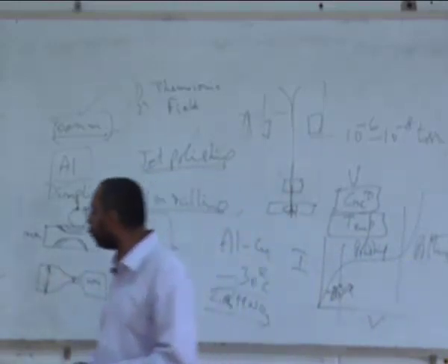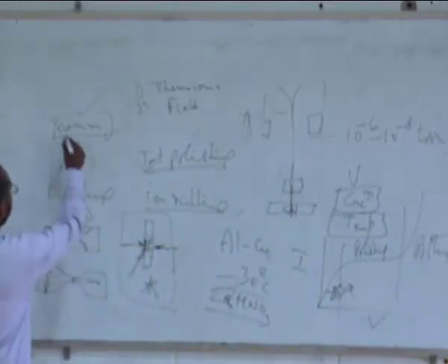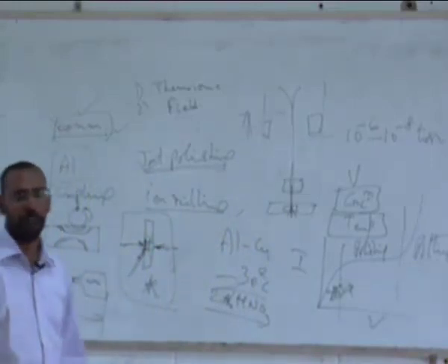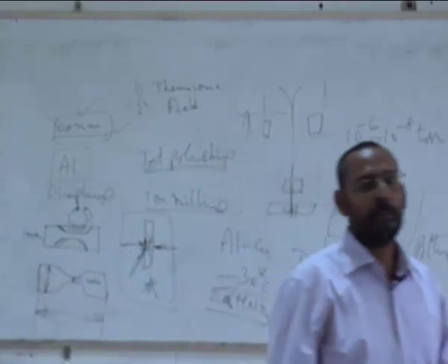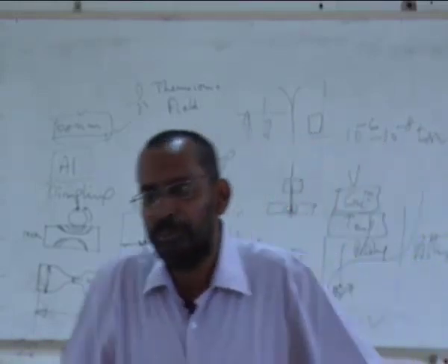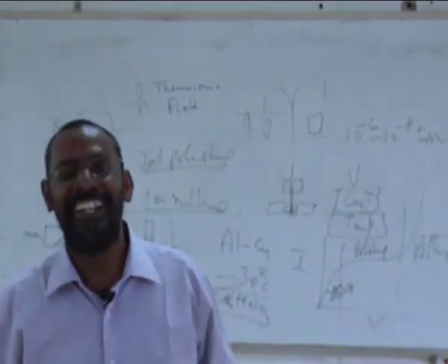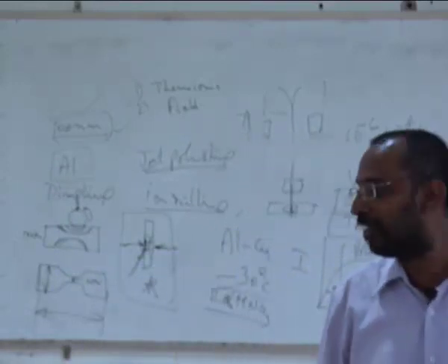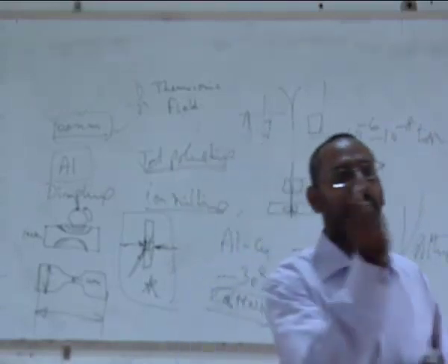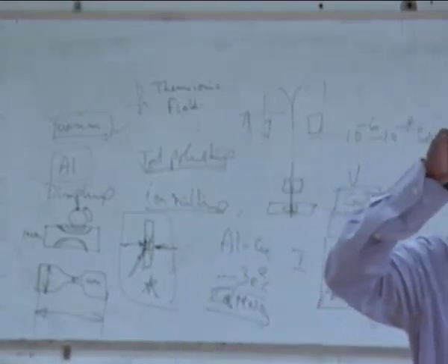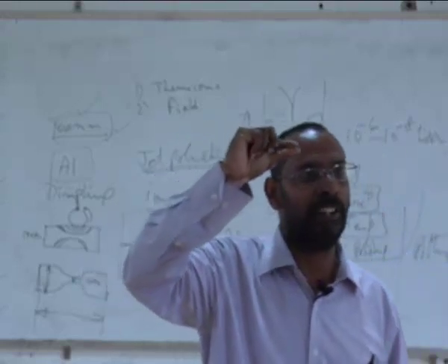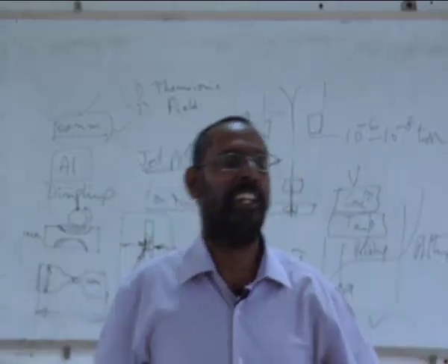The second aspect that you also need to know is that not only the thickness, the diameter of the sample is also very important. In a TEM, the biggest sample that can go into the TEM is only 3 millimeters. Imagine what we are actually seeing. I am seeing a sample which is 3 millimeters. Can you imagine 3 millimeters? So a 3 millimeter disc with a thickness of 100 microns starting and finally finishing with 100 nanometers is what I am actually seeing in the TEM.